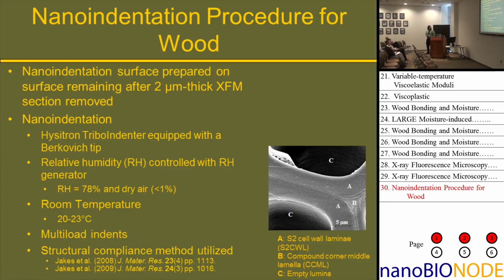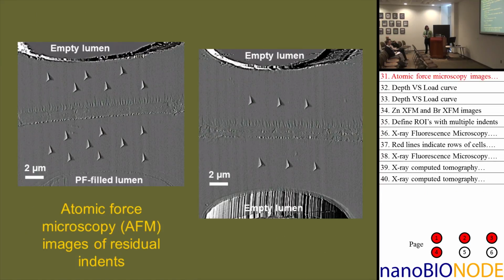Nanoindentation with the Hysitron TriboIndenter with the Berkovich probe. Then we're going to control the humidity inside the enclosure using an RH generator, so we can look at the effects of moisture-induced softening on the cell wall properties. Just at room temperature, and multi-load indents to account for the potential effects of edge effects and specimen flexing. So here's just an AFM image of some of the residual indents that we placed inside these cell walls.